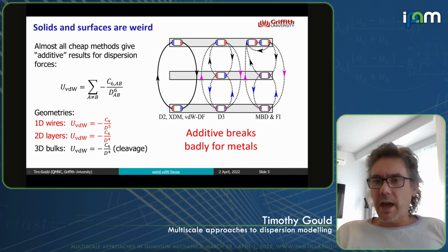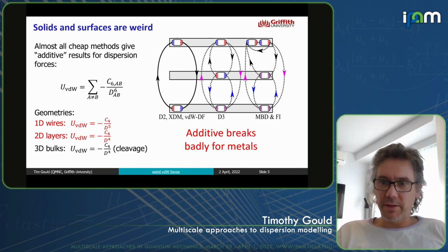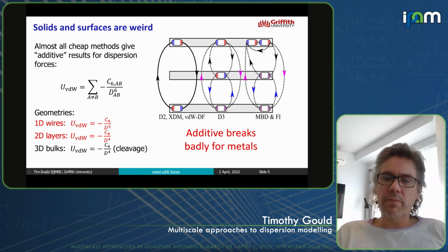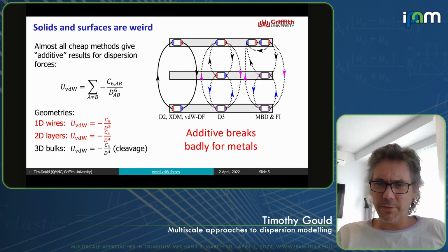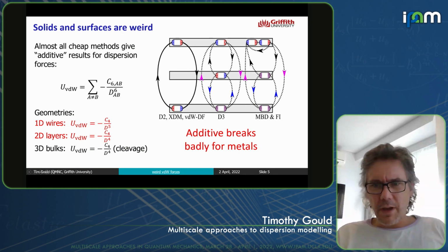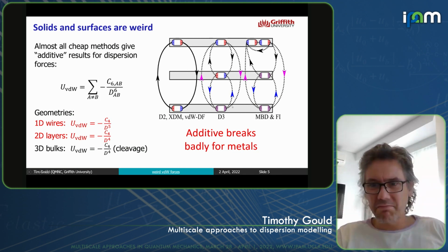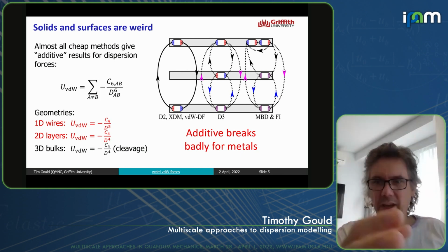Now, if we have 3 atoms, this is long enough known that it has its own special name. It's the Axilrod-Teller-Muto term. And we basically just look at the combined interaction between the 3. So, for example, our positive charge here and negative charge here is definitely going to set up a negative here and a positive here. Now, down the bottom one, probably this is going to be a positive, but it's going to be a little bit of a weaker positive because the one up here is positive. So what will actually happen is everything will stabilize into a 3-way coupled fluctuation.